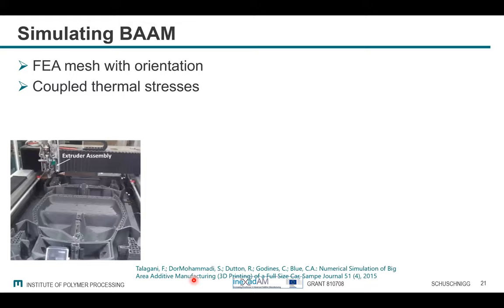How do these thermal stresses happen? They happen because the PVT data showed us that we have a shrinkage of the hot polymer. It solidifies and cools down, and then it shrinks. And in additive manufacturing we put one layer of material, and then the next layer of hot material, and the other cools down.